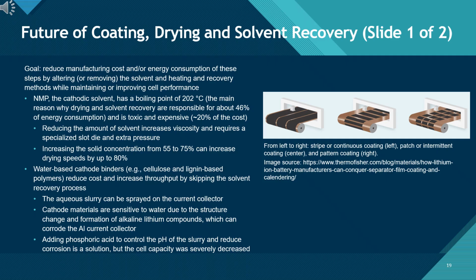Reducing solvent content can dramatically speed up drying. Higher solid loading can increase drying rates by up to 80%, but also increases slurry viscosity, requiring specialized slot die configurations and higher pressure. A major research direction is replacing NMP with water-based binders such as cellulose or lignin derivatives. These systems can eliminate the need for solvent recovery equipment and increase throughput, but they introduce challenges.